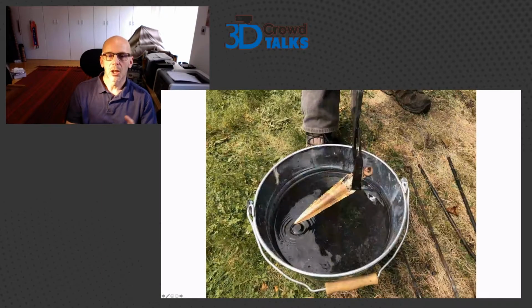and breaking open, I can actually take the original thing out. We've changed now to a different day. This is a little, hopefully obvious, sharp, what's called a tanged spearhead. That was also 3D printed from an original, and I made a batch of these that were used in a film where they were reenacting spears from that particular time. So this is then quenching this 1,000-degree cast heat into handleable cold temperature very quickly. It all happens really quite quickly. It's quite magical, actually, seeing the molten metal turn into a hard object like that.